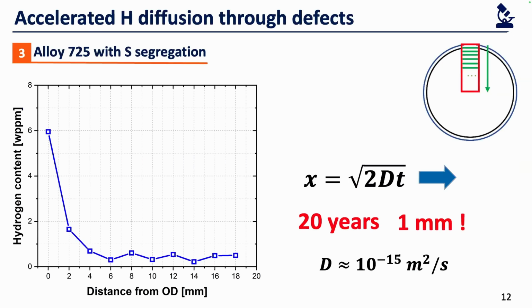So let's come to the diffusion. We measure the hydrogen content from the surface of the drive screw towards the center, and we observe that hydrogen penetration depth can reach up to 4 millimeters. But if we take a look at the hydrogen diffusion coefficient in the literature and make a simple calculation, after 20 years, we can only estimate that hydrogen can penetrate inside the material for only 1 millimeter. So what was happening there? Why do we observe such a large hydrogen penetration depth?